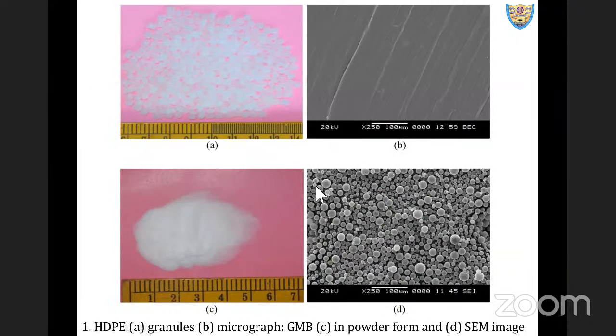So what you see here is the HDPE and its scanning electron microscopic image. We do this for as received systems to look at the texture. And this is the bunch of glass microballoons, which look like this. These are engineered ones having a diameter of around 15.3 microns, which we are going to now mix. What I talked about previously was Cenosphere. I'm now talking about the glass. So this glass we're going to mix in the high density polyethylene.